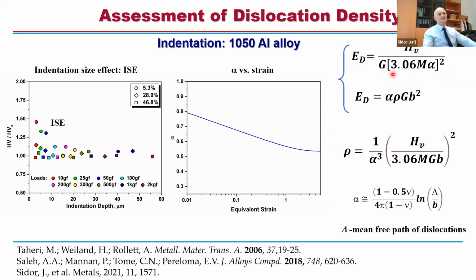And they proposed this simple formula where basically you need to know the Taylor factor, G is the shear modulus, and alpha is what we call a geometric constant. But for this geometric constant, typically people assume that it's 0.5. However, when you do a more precise calculation of this geometric constant, you will see that for mixed screw and edge dislocations, this alpha tends to increase at lower thickness reductions, right? So it might change from 0.8, and in fact, after a certain degree of straining, it saturates at 0.5, right? So for each strain increment, you can calculate the alpha.